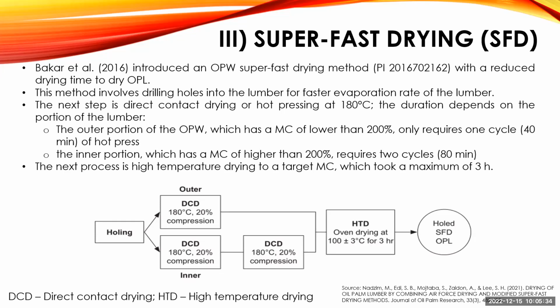For direct contact drying, we use a hot press at 180 degrees Celsius that compresses slightly to reach a 20% compression ratio. The most important thing is to separate the outer layer and the inner layer - for the outer layer you use one cycle of direct contact drying, and for the inner you need two cycles because it has higher moisture content.